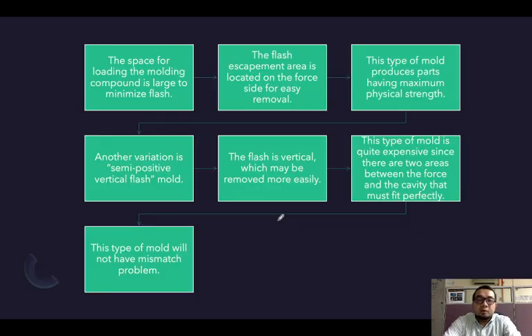So the space for loading the molding compound is large to minimize flash. The flash escape area is located on the force side for easy removal. This type of mold produces parts having maximum physical strength. Another variation is semi-positive vertical flash. The flash is vertical, which may be removed more easily. This type of mold is quite expensive, since there are two areas between the force and the cavity that must fit perfectly. This type of mold will not have mismatch problem.